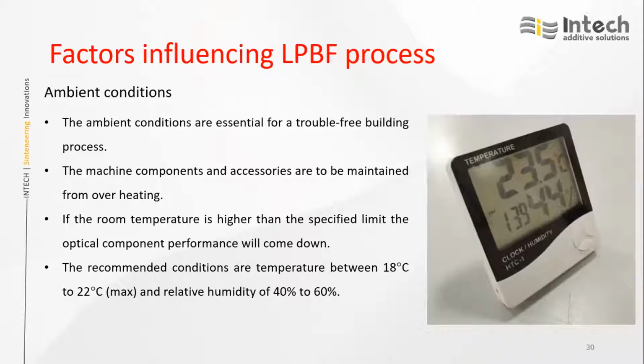Conditions at which the operation is happening are also very important, because the laser and the scanner mirrors will always be maintained at certain temperature. Small deviation there will affect the part geometries, and all those problems will come into picture. So the typical temperature which needs to be maintained is 18 to 22 degrees and relative humidity of 40 to 60%.